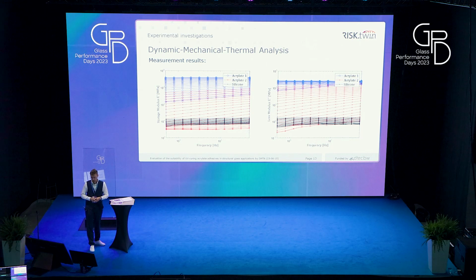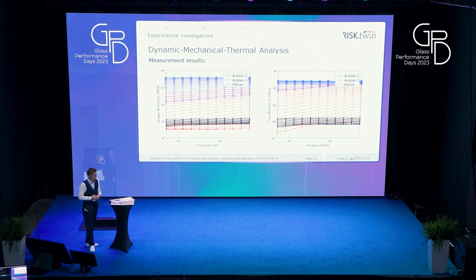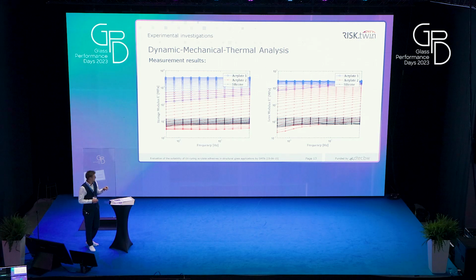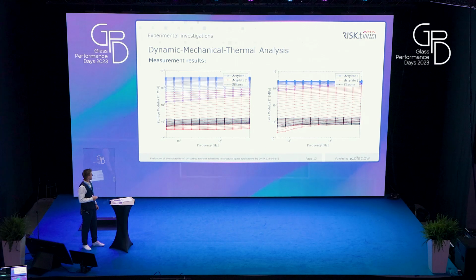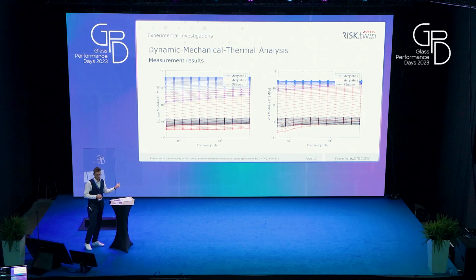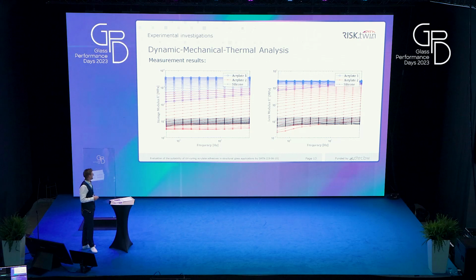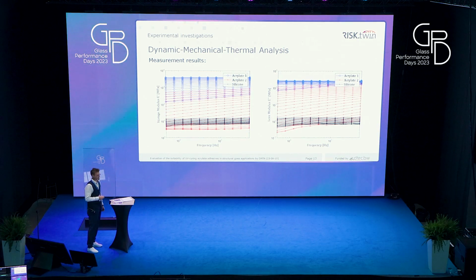Another interesting plot is to plot the results over frequency. So here now, every line represents a specific temperature, whereas in the picture before, every line represented a frequency. And again, we can see here the constant behavior of the silicone. And now you can see that I actually lied to you, because for acrylate 1, I said we have no strain rate dependence. But this is actually valid only for lower temperatures up to 20 or 30 degrees Celsius. And the lowest blue line is the line for 80 degrees Celsius, and here we actually have a difference between 0.5 hertz and 50 hertz.